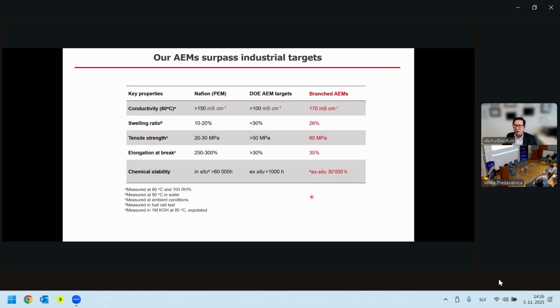We can compare our membrane properties to industrial standards or targets. I already mentioned certain things, for instance, conductivity or mechanical stability, which is typically characterized by tensile strength or elongation at break. We talk about chemical stability, and the swelling ratio is related to mechanical stability, and so on. People can compare to Nafion as a benchmark. The U.S. Department of Energy also has certain targets, and this is our branched AEM. In terms of conductivity, we have hydroxide conductivity of more than 170 millisiemens. So this is really on the higher end, one can imagine.